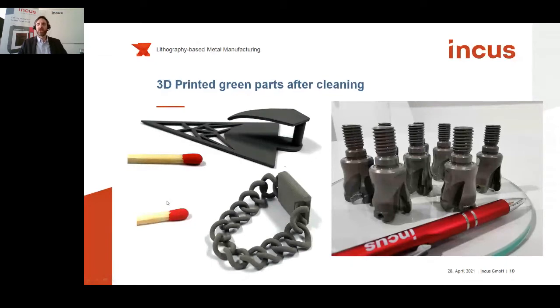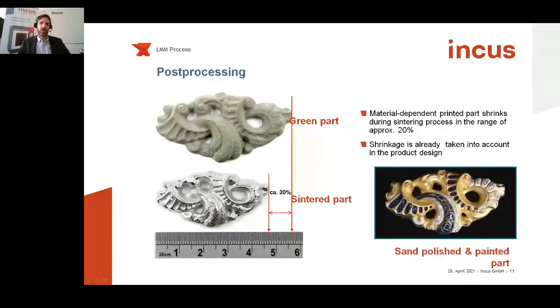You need to do a thermal post-processing, or the debinding and sintering step. And this is also a very, very important process step, of course, because here you generate the final metallic properties. So you see the direct comparison of the printed green part on the top, and on the bottom is the sinter part, also in this case with stainless steel. And you have a shrinkage of roughly 20% in every direction.